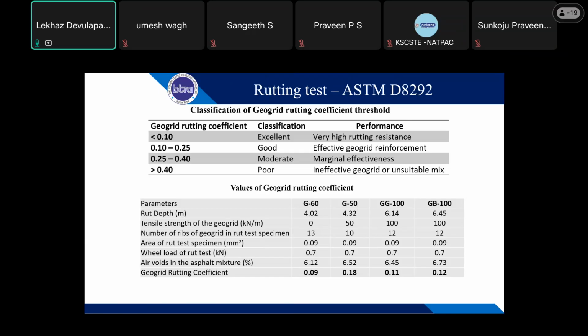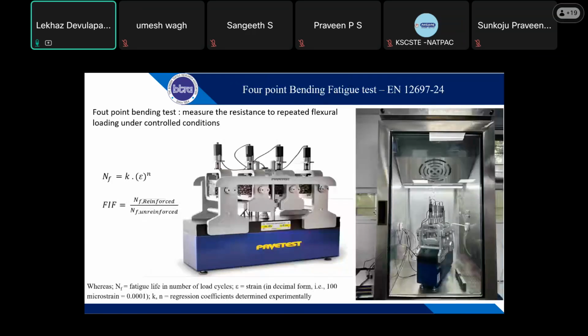the G60, and even the geogrids are performing well, whatever the tensile strength of the geogrids, which is nearly 100. Even though it has a 50 kilonewton strength, it has a high number of ribs, and it has given a good resistance compared with the other grids. Once we did the rutting test, we got good values when compared with the control mix.